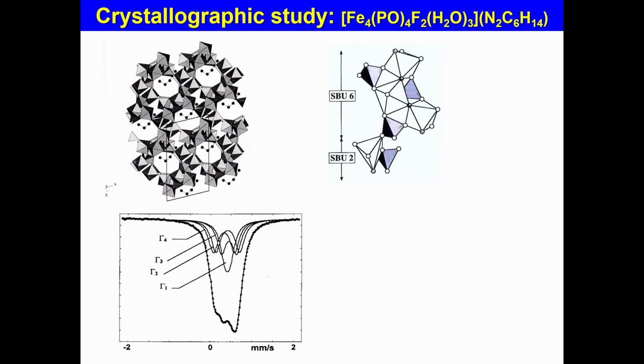So we have done some Mossbauer spectrum at room temperature. We put 1 component, 2 component, 3 component, 4 component, it was okay. And if you look carefully here at the positions of the doublets, you can correlate each doublet to a unit, because the isomer shift is also sensitive to the number of neighbors. So the isomer shift of tetra is smaller than the isomer shift of hexa and smaller than the isomer shift of octa. It was possible to attribute them, and in addition, the quantity of each one was in agreement with the crystallographic prediction.